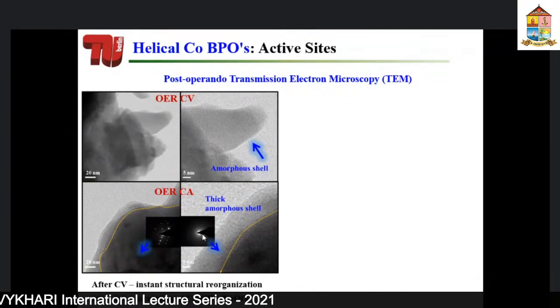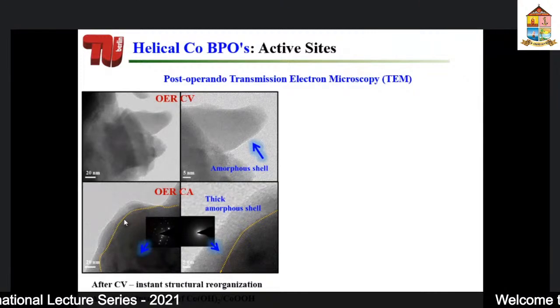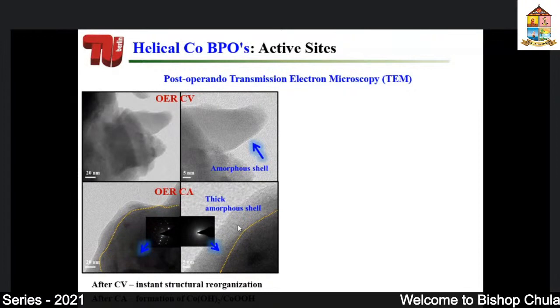and if you have no spots here, that means the material is amorphous. And what you see is that this area here is crystalline, but the surface changes. So this means that we have a large change at the surface, which is forming an amorphous shell. So our catalyst is not a real catalyst, but it's a pre-catalyst. So now we have to know what is the structure of this catalyst.